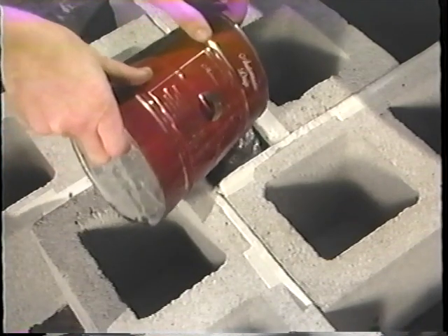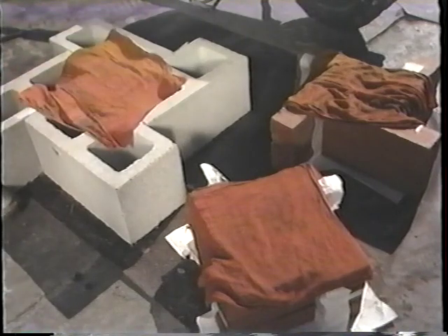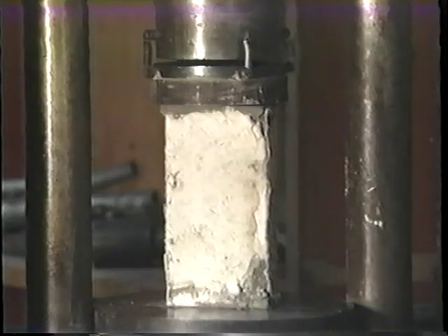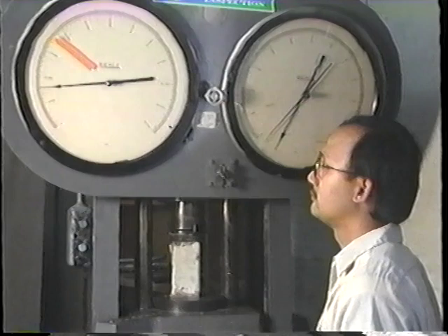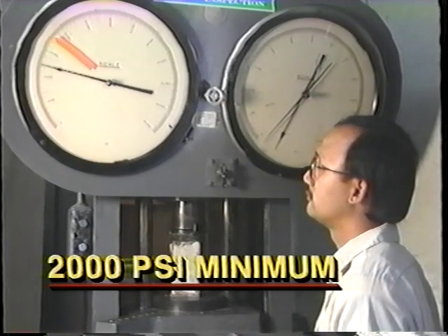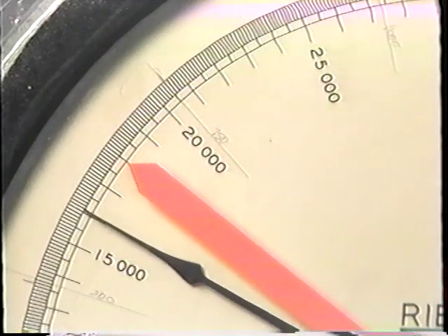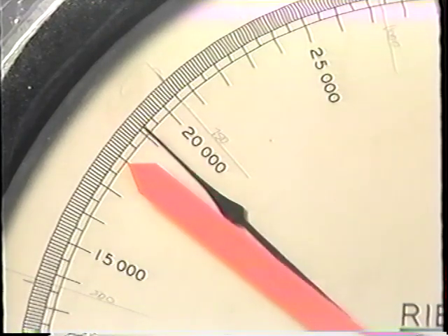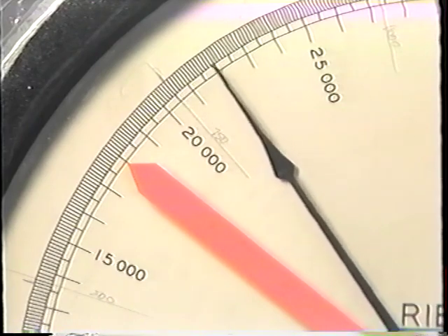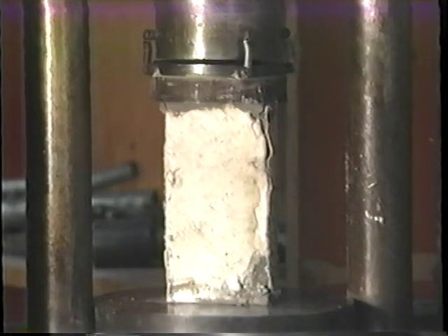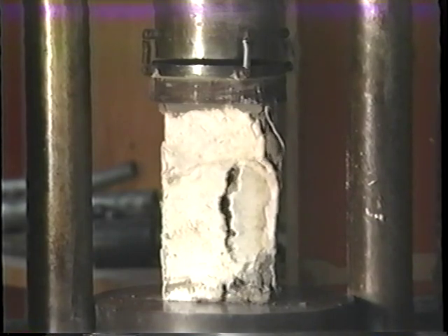A representative sample of the grout is placed into molds in 2 layers, puddled, and kept damp and undisturbed until taken to the laboratory, where it is placed into a fog room until tested. Both fine and coarse grout must have a minimum compressive strength of 2,000 pounds per square inch. This compressive strength ensures bonding of the grout to the reinforcing steel. This specimen was tested well beyond its minimum load.